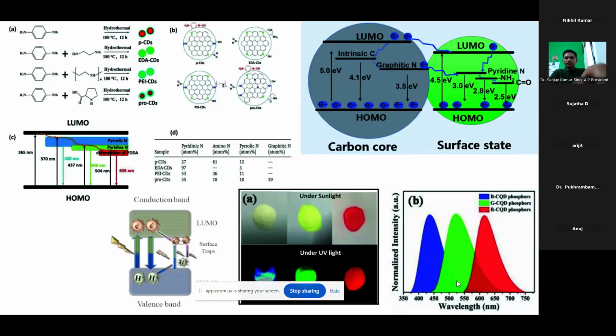Next, other types of functionalization. N doping we can do with a simple nitrogen precursor. When we take the carbon precursor, we have to add the nitrogen precursor into it. Then with hydrothermal or microwave, whichever we opt for, we can achieve this CQD. With nitrogen doping, we can optimize where it goes according to the application we need. We can do pyrrolic, pyridinic, or graphitic nitrogen doping. If we are taking it for solar cells, we have to do graphitic doping. If we are doing it for electrochemical application, it's obviously pyrrolic.